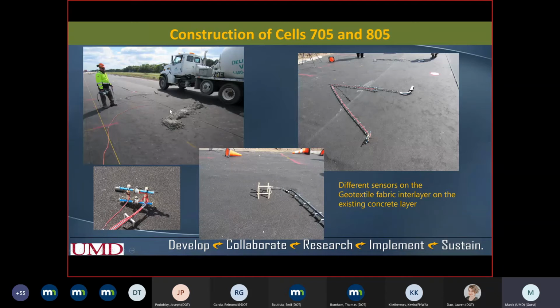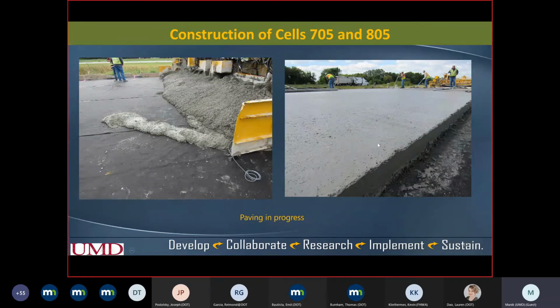These are some pictures from during the construction time. Some sensors you can see installed, and this overlay was constructed as an unbonded overlay. You can see a geotextile fabric interlayer was used on top of the existing concrete before placing the new concrete. These are some more pictures here. This is the finished product.